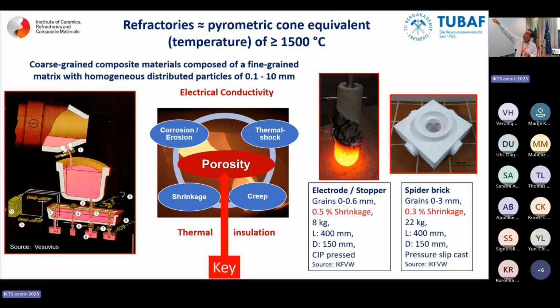Yes, we see here a stopper, as we are doing in Freiberg, a self-glazing system, or a pressure slip casted spider brick. You see, we have coarse grain systems now, and the coarse grains can become much bigger. Somebody would say, on the one hand, you deal with corrosion and erosion. This is positive. Creep is positive. For the coarse grains, shrinkage is one very important issue. Imagine we don't speak about small samples, but bigger samples in metal. And especially everything that deals with thermal shock, we have seen yesterday very nicely the impact of pore size distribution and pore morphology. So one key to get the compromise is the porosity and how you can distribute it.